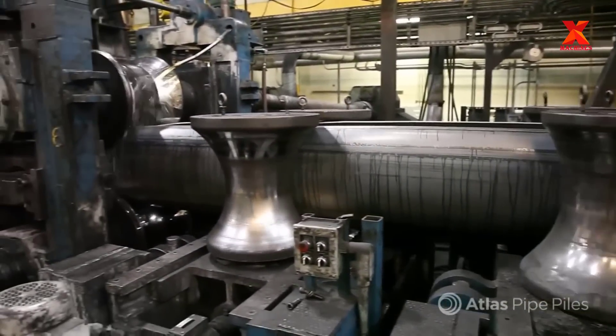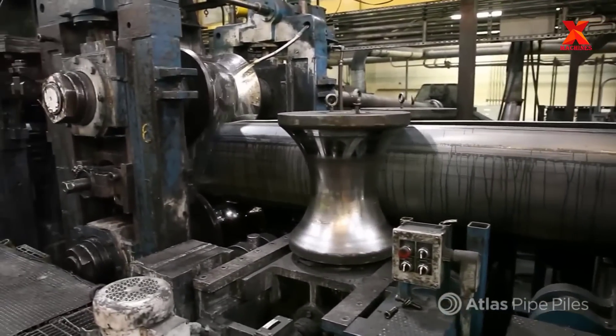Finally, the rolling presses change from convex to concave and gradually push the ends together. In this step, they line up evenly and the strip edges are burnished clean to ensure a high-quality weld in the next step of the process.